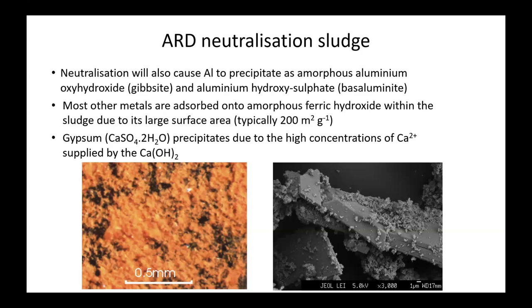Along with the precipitation of the iron, you get precipitation of the aluminium. So it will precipitate either as amorphous aluminium hydroxide, often called gibbsite, or aluminium hydroxysulfate, basaluminite. So the equivalent of schwertmannite and ferrihydrite.